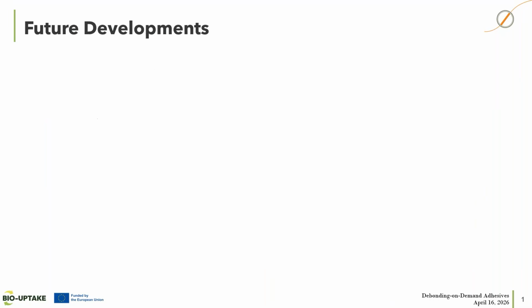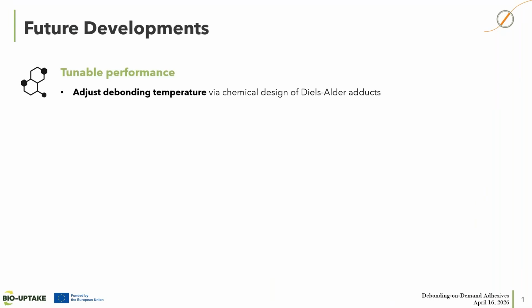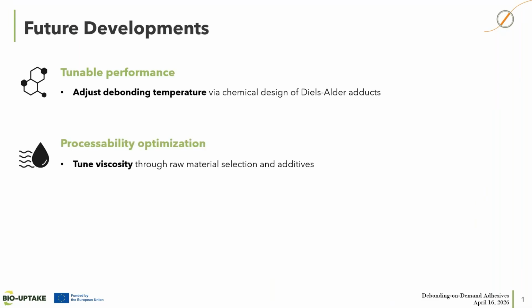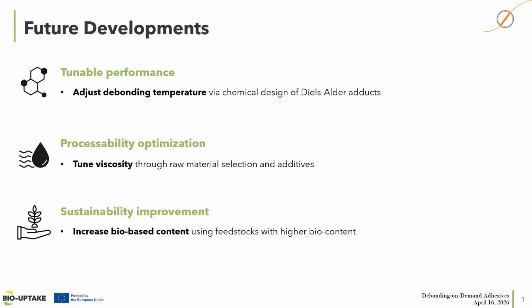So, based on this proof of concept, we are now working on 3 key aspects. First, tuning the performance, especially by adjusting the debonding temperature through the chemical design of Diels-Alder adducts. Secondly, the optimization of the processability, for example, by controlling the viscosity with additives or through raw material selection to expand the range of possible application methods. And third, the improvement of the sustainability by increasing the bio-based content of our formulation.